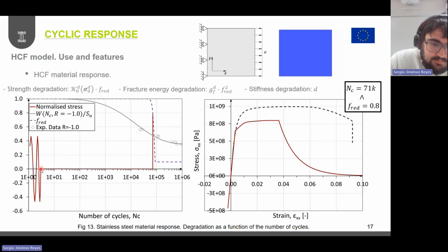And you can see here this big jump corresponds indeed to the advancing time strategy. So you can imagine that each of these cycles is being described through, in this case, each cycle it's 8 steps in the numerical simulation. So imagine trying to go through these nearly 100,000 cycles, well, these 71,000 cycles without an advancing time strategy. And I've done the same for other amounts of cycles.